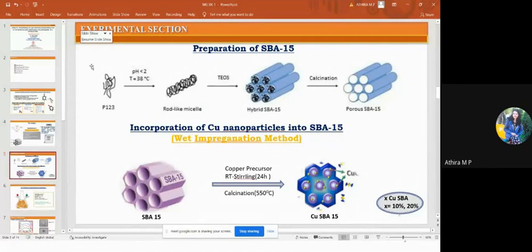Next is the preparation of catalyst. Catalyst synthesis includes two steps. The first one is synthesis of SBA-15: hydrochloric acid, Pluronic P123, a block copolymer, and TEOS are mixed well and placed in an autoclave for 48 hours. The obtained material is filtered, washed, dried, and calcined. The next step is copper incorporation, which was done by the wet impregnation method. The prepared SBA-15 is treated with a copper precursor and calcined at 550 degrees Celsius. Catalysts with different copper weight percentages were prepared by varying the copper content, denoted as X Cu-SBA, where X may be 10, 20, 30, etc.